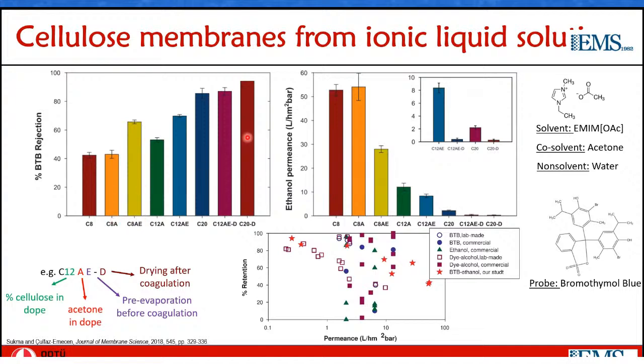All these increases in rejection were also accompanied by decreasing permeances. But overall, our membranes, which are shown in stars in this plot, together with lab-made or commercial membranes, in filtrations of bromothymol blue or other dyes in ethanol or in other alcohols taken from literature, the membranes that I mentioned here are quite comparable to other membranes reported for organic solvent nanofiltration.